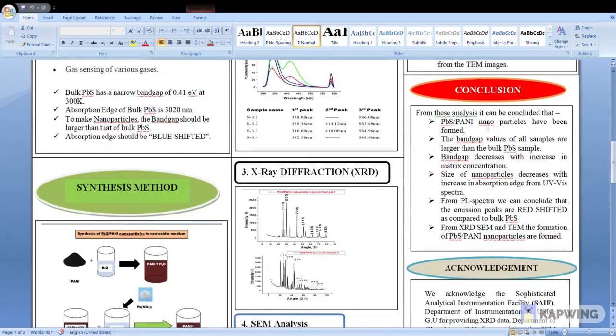In conclusion, from this analysis, we concluded that lead sulfide PANI nanoparticles have been formed. The band gap values of the samples are larger than the bulk lead sulfide sample. Band gap decreases with increase in the matrix concentration. Size of the nanoparticles decreases with increase in the absorption edge of UV visible spectra.